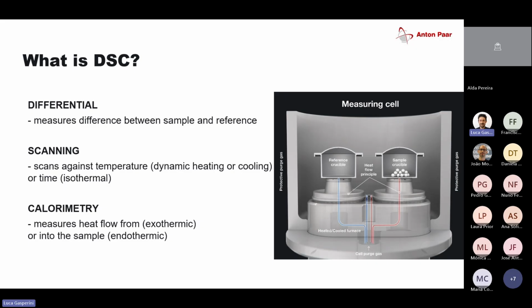And on the picture I have a cross-section of a measuring cell. Let's see which is the laser, this one. So the sample is in most cases encapsulated in a sample holder, which we call a crucible. Then we have basically exactly the same type of crucible on the reference side. The furnace is either heated or cooled. We also run some gas, which creates the atmosphere in the furnace, depending on whether we're interested in inert atmosphere or oxidative atmosphere. That's based on the application. And we also run the gas around the furnace for the purpose of getting any unwanted moisture out and creating a stable environment for the whole measurement setup.